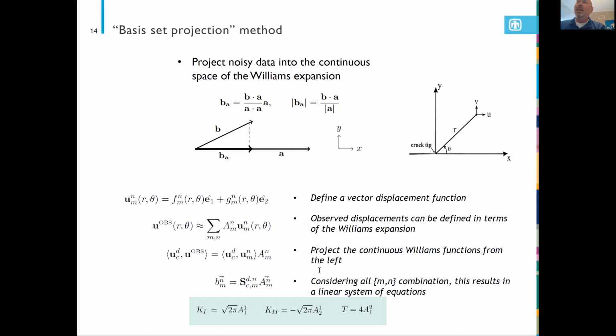Okay, I note that this is a very compact form. The size of this matrix happens to be 2n plus 2, where n is the number of terms that you want to use in the Williams expansion. This is very small relative to a linear least squares approach, which would require an overdetermined system where the number of rows in the matrix would be consistent with the number of points that you chose within the number of atoms that you chose to model the displacement of. So it's very compact. Again, we're looking for the stress intensity factors, which are associated with these given coefficients.